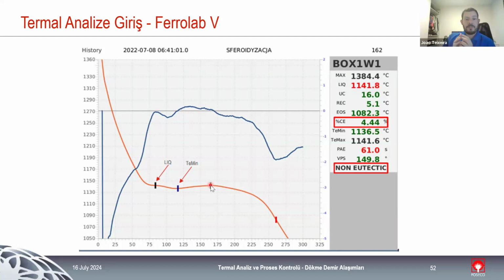For gray, for example, the window is between 3-4 degrees and 7 degrees. It is a little bit higher because for nodular cast iron, we are forming a perfect round nodule. So the amount of latent heat released is lower than gray cast iron or compact cast iron.